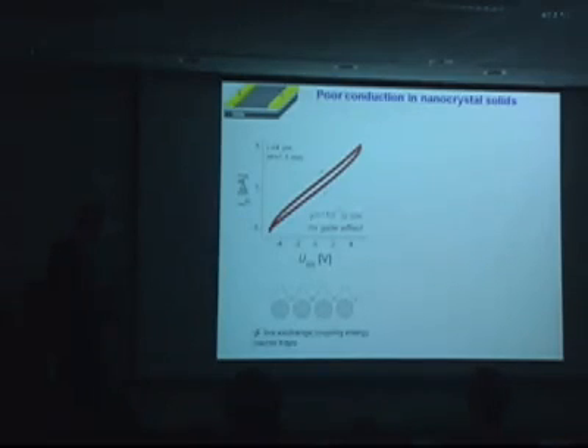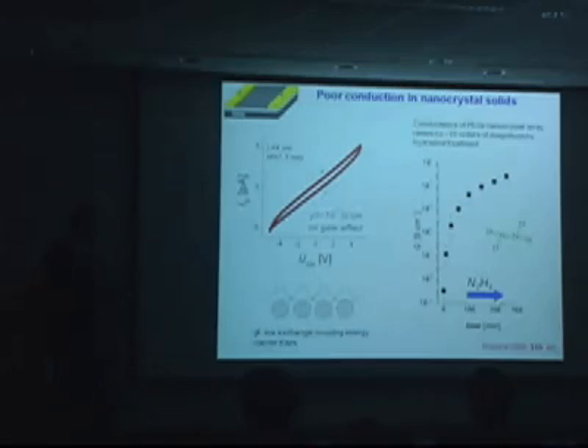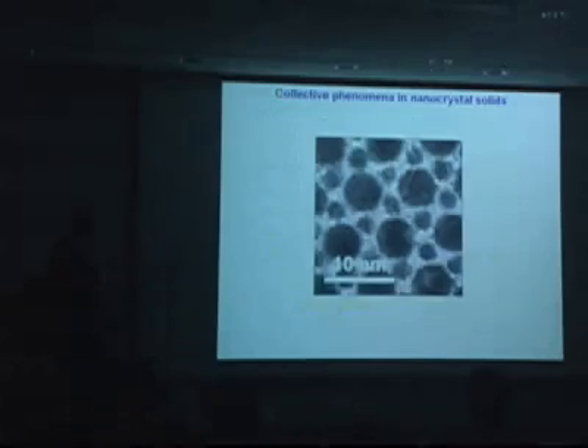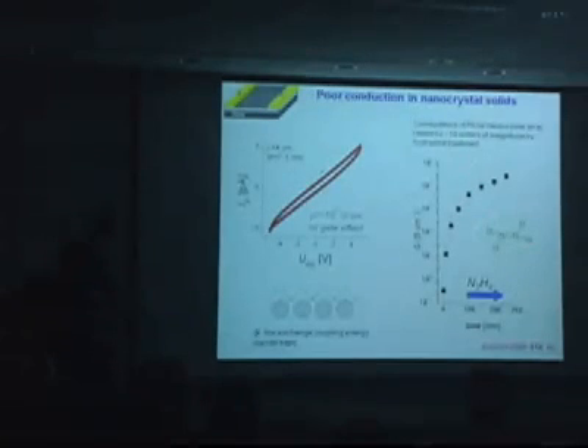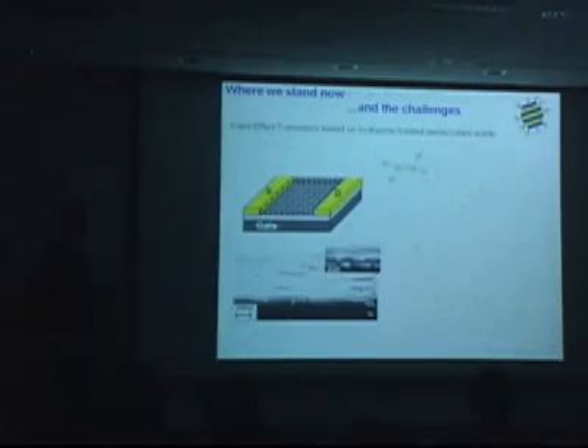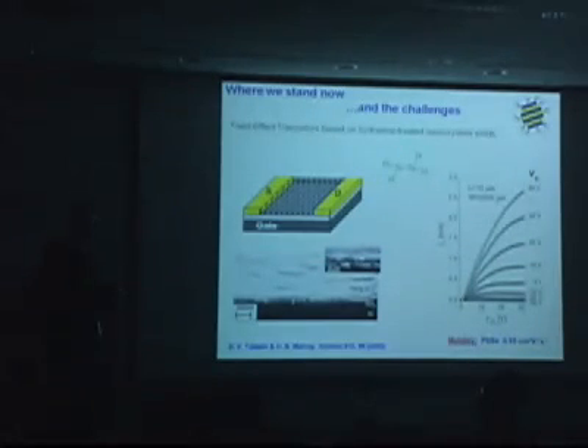And some years ago we found a nice trick to improve conductivity in a very simple fashion by 10 to 11 orders of magnitude. We found that we can replace these bulky ligands with a small molecule, hydrazine, using dilute solutions of hydrazine in acetonitrile, and that increases conductivity very quickly and by orders of magnitude. We just started with colloidal solutions, treated them with a 1 molar solution of hydrazine in acetonitrile, and converted a pretty good insulator into the first field effect transistor made out of nanoparticles.